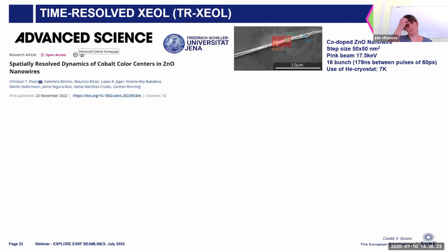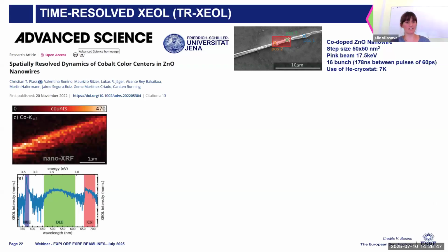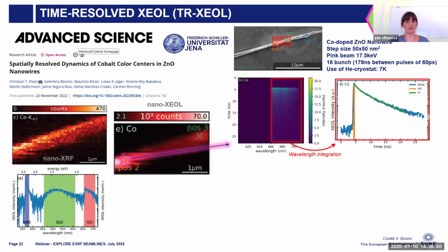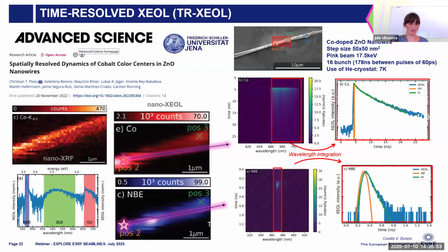So the scientific example to illustrate this technique is the study of the dynamics of cobalt color centers in the zinc oxide nanowires that you can see here on the top right. The sample has been mounted in a helium cryostat to work at 7 K. I will talk about the cryostat later on in the presentation. And so the nanowire has been scanned with the fluorescence, but also with the XEOL. And what we can actually see on this map is that there is a variation in the concentration of the cobalt.